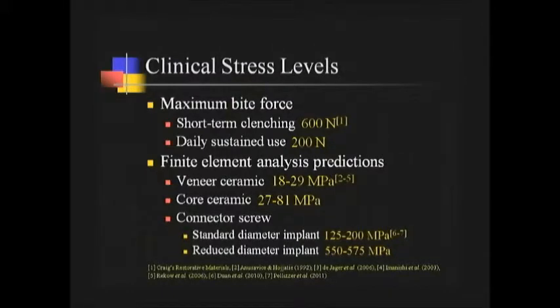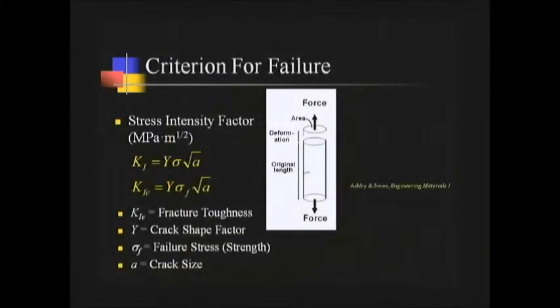And these stress levels are lower than the yield strength, and of course lower than the ultimate tensile strength of titanium. So just considering the information we have on this slide, we would expect to never have a failure of a restoration or an implant, and obviously that doesn't happen. So something must be happening over time. When the implant is first placed, when the restoration is first placed, the bite force is not enough to cause failure to happen. Something changes over time. That's the subcritical crack growth that you and Ulrich have been talking to you about already.